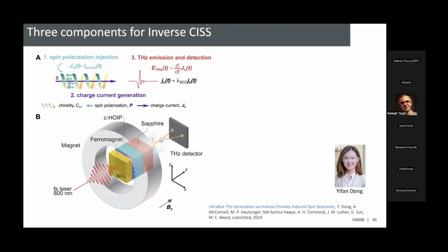So this is work from Yifan. Instead of using a metal, we're going to use a chiral perovskite. So a ferromagnet over here in contact with the chiral perovskite. And now we're going to have the spin orientation out of plane and use a femtosecond laser pulse to generate this spin current that gets injected into the chiral perovskite, and then measure the charge current that's induced. Importantly, as I mentioned, terahertz spectroscopy can get both the direction of that charge current that's generated, as well as the polarity. So I can tell if it's going forward or backwards, and which direction it's going in.